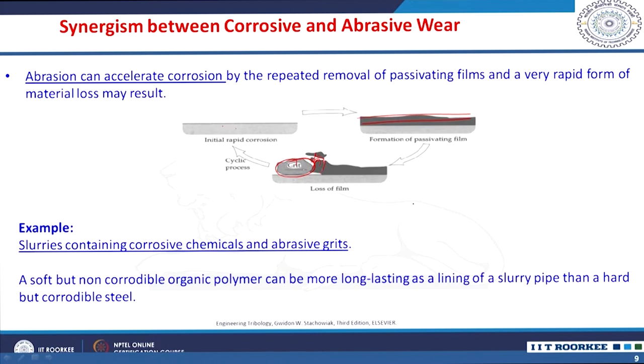Abrasion actually accelerates the corrosion by the repeated removal of passivating films, and a very rapid form of material loss may result. So, you can find such synergetic effect of corrosive and abrasive wear in slurries containing corrosive chemicals and abrasive grits. A soft but non-corrodible organic polymer can be more long lasting as a lining of a slurry pipe than a hard but corrodible steel.